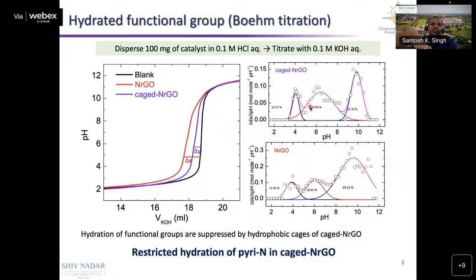Furthermore, as I told, when we talk about hydration of these molecules, hydration involves the functional groups. This nitrogen catalyst has different functional groups, like COOH, OH, and NH groups. If there is hydration, there will be interaction with water molecules there. So we tried to map it out by Boehm titration, where we can calculate the exact amount of hydrated functional groups. At different pH values we can quantify the hydrated functional groups, and we can say which has higher hydrophilicity and hydrophobicity, because hydration is one of the effects responsible for the lower activity of this catalyst.